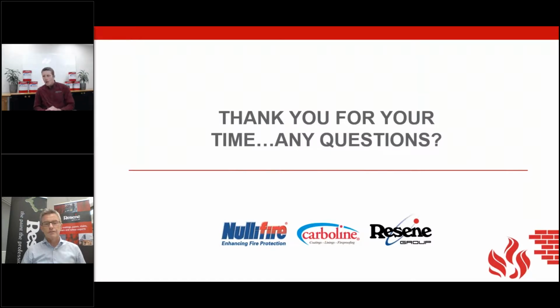Absolutely, absolutely. So when we're talking about loadings, we're talking about the actual dry film thickness that's required for a particular steel member to give its 30 or 60 or 90-minute rating. So again, that's what's been tested with each individual product. Each individual product will have a different DFT for a different section of steel. So for example, you will get a different film build thickness on a 100 by 6 SHS compared to, say, a 310 UB40 beam or column. As to information-wise, we certainly need to start with, obviously, what's the fire rating on it. You would be surprised how many times that we don't get that information.